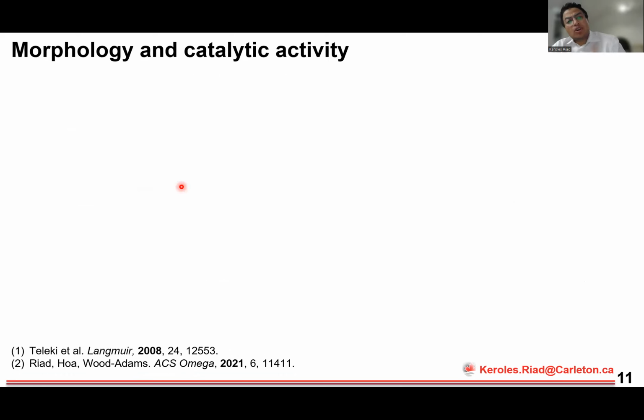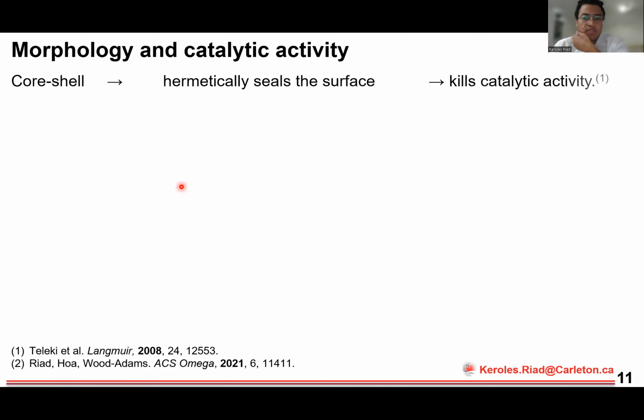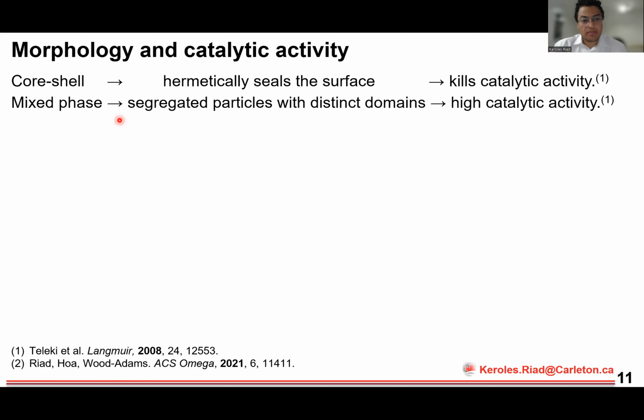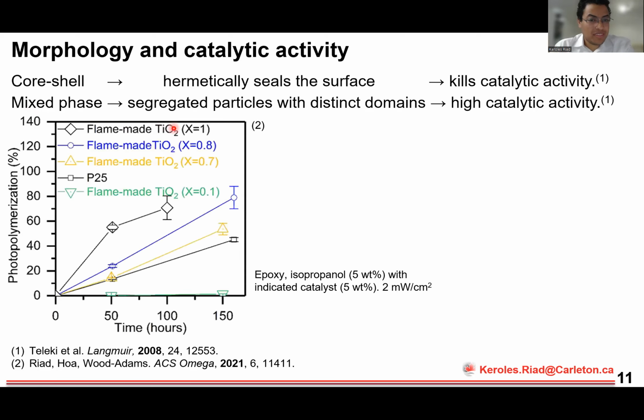Now, with catalytic activity, you also have to think a lot about morphology, especially when you have an amorphous matrix. And I go back here to the work with Professor Taliki, who compared a core shell structure where the amorphous matrix would hermetically seal the surface, which would actually kill catalytic activity, compared to mixed phase particles where you have segregated particles with distinct amorphous and crystalline domains, which actually have a high catalytic activity. And so I think the proof in the pudding here was catalysis.